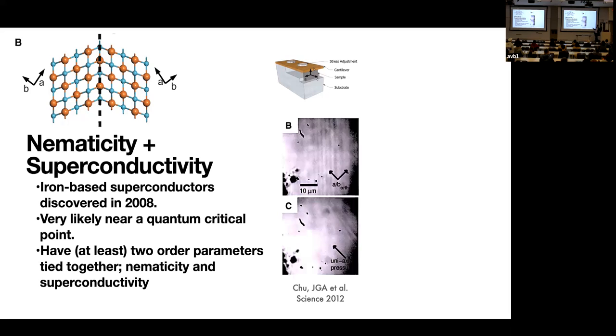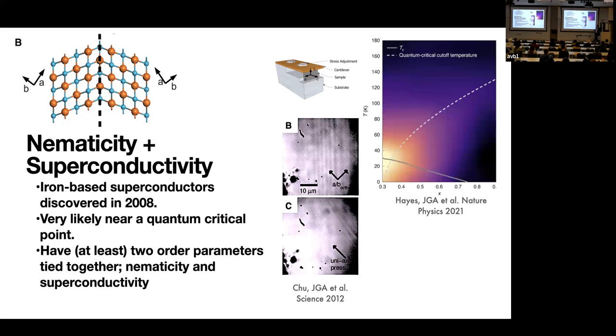And you can see that, well, we didn't have quite as good images as the Tanatar and the Canfield group, but you can see that these domain walls, these dark lines and white lines, would disappear as soon as we applied strain. Now, the reason why we wanted to do that is we wanted to couple to that broken symmetry inside the system and discover what it truly was.